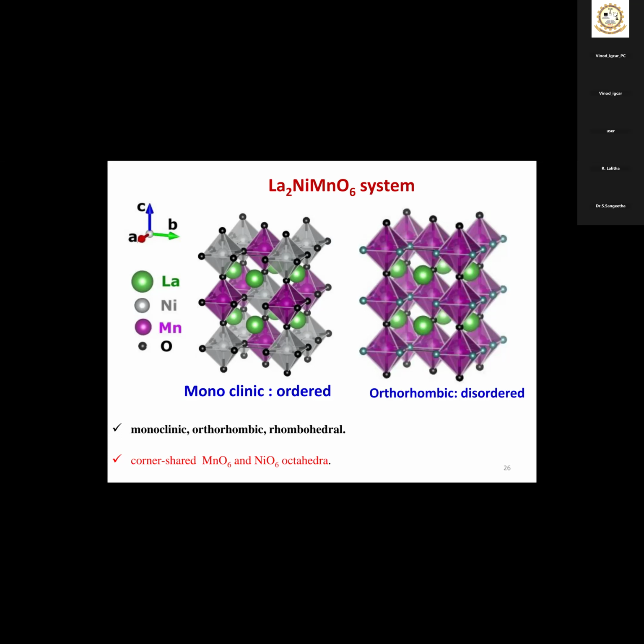These two will have a different crystal structure and different magnetic property, because now your nearest neighbor exchange interactions are changed. See, your metal-oxygen-metal bond is changed. In the left case, the bond is always manganese-oxygen-nickel. So your exchange interaction is fixed with that.